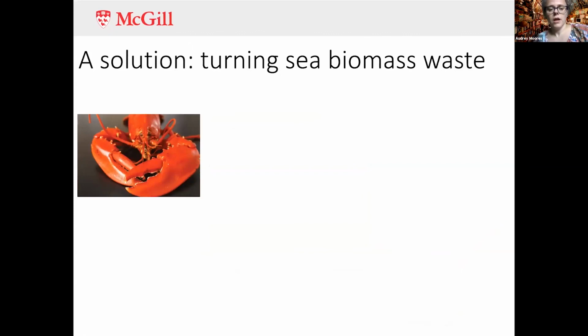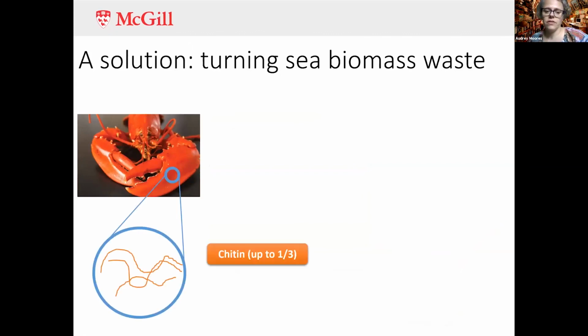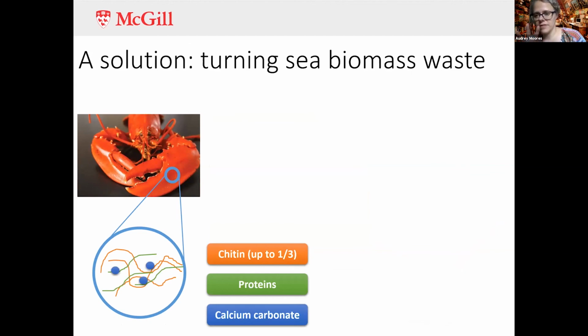So if you take a crustacean shell, we can dive into this a little bit to understand the structure a bit more. So again, following the past presentation, we have learned that inside the crustacean shell, we find this polymer called chitin. There's also some proteins that are left, which, if you can extract them, are interesting materials as nutraceutics. And through this network of two polymers, we have calcium carbonate present as small particles, and they confer toughness to the ensemble. What you want to do when you take this is find a way to take out a material that is interesting in it, which is chitin.